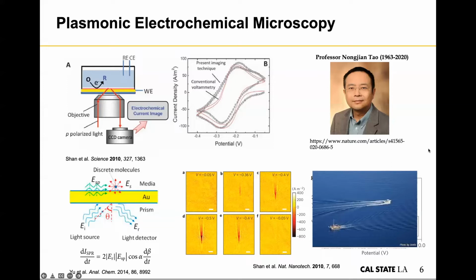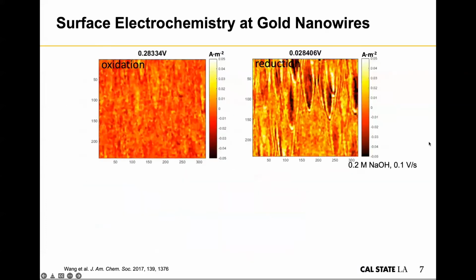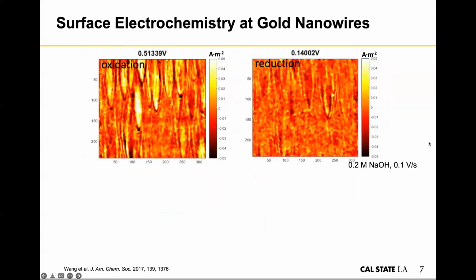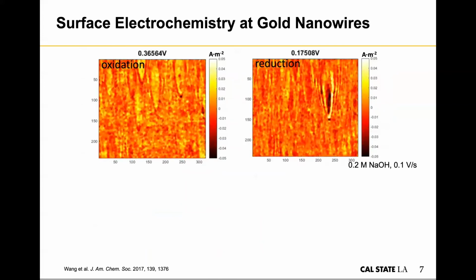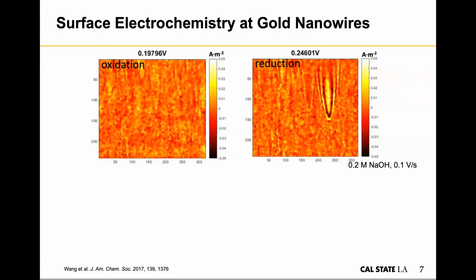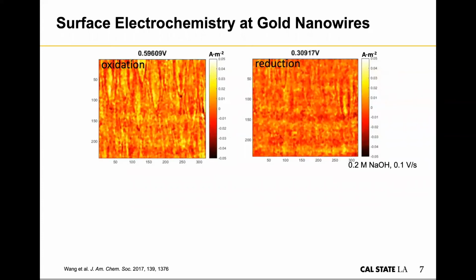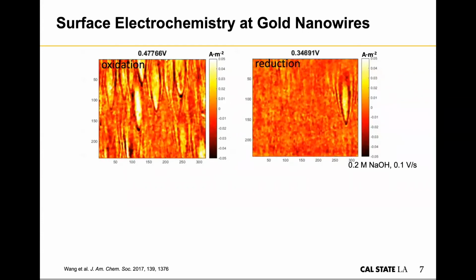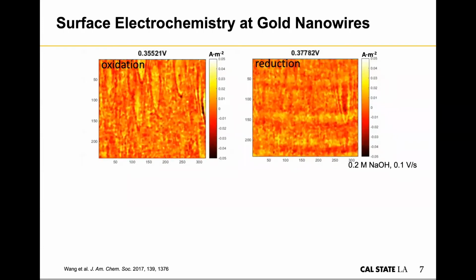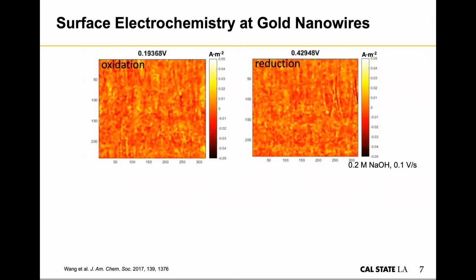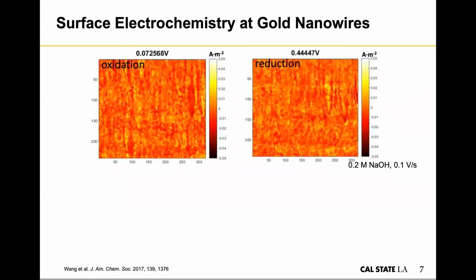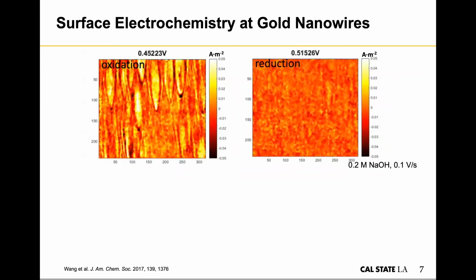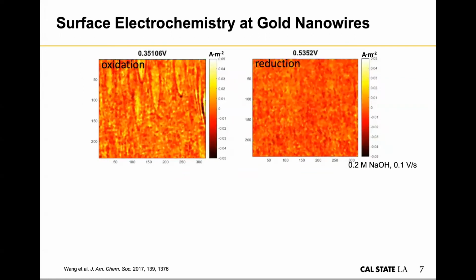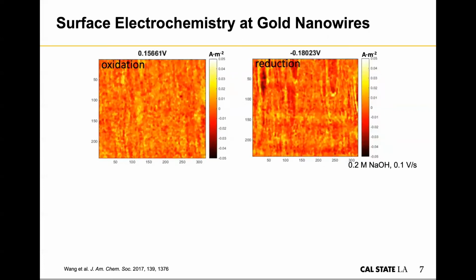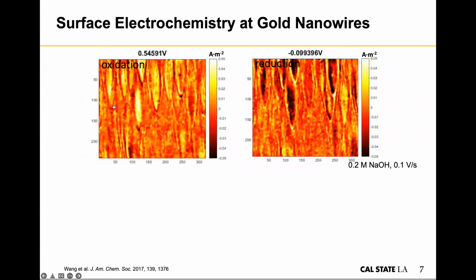And then I will start talking about two examples using this technique to study single nanoparticle electrochemistry. The first part is what I did as a postdoc in Dr. Tao's lab. We used this technique to study the surface electrochemistry at gold nanowires. The system is very simple. We're simply looking at the surface of the gold particle, conversion from gold to gold oxide, and then conversion back from gold oxide to gold. The original motivation of this work is that we know the surface reaction is sensitive to the surface facet of the particle, so we would like to see whether we could get structure information out of observing different combinations of nanoparticles. Now here I'm showing you two videos. The first one is the oxidation process of the gold nanowire.